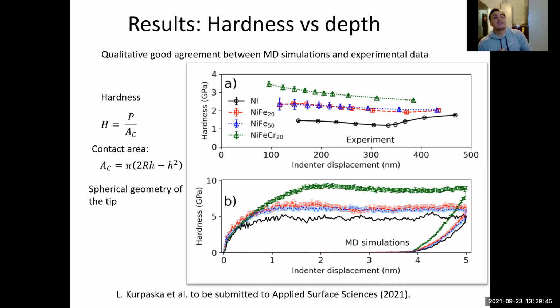So we have more results. Now we need another correspondence between the experimental data and the MD simulations. In the experiments, they can calculate the hardness as a function of the indenter displacement. And the reported result is that nickel is really soft. And then when you add iron and chromium to the sample, the hardness value of the material increases. They found that in the experiments, very nice. But we also found it in the MD simulations. You can see here we have this correspondence.